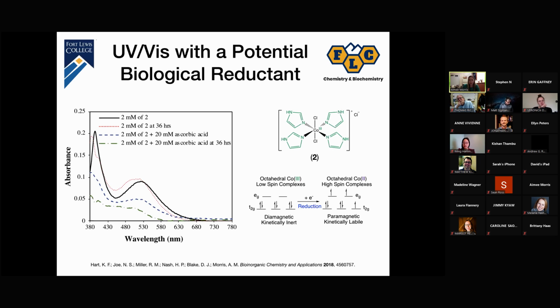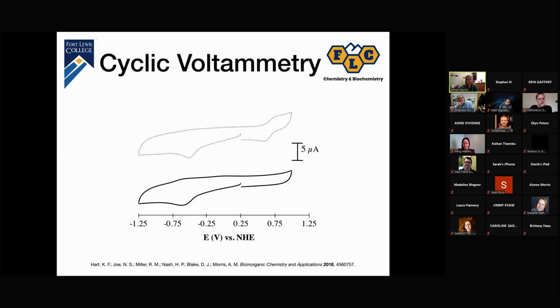So, the next thing we looked at was some cyclic voltammetry. So the top dotted line one has the internal standard ferrocene in there to see your ferrocene to ferrocenium couple. And the bottom is just our cobalt compound. And so you'll see as we progress towards more negative applied voltages, we see the cobalt 3 get reduced to cobalt 2. This is actually an irreversible reduction that happens within our cobalt compound, which again is very common in similar cobalt 3 compounds with multidentate ligands. So there's likely a change in structure. Once you reduce cobalt 3 to cobalt 2, there's likely some other ligand substitutions and changes in structure that happen. And in fact, we see evidence for that even in the cobalt 3 state.